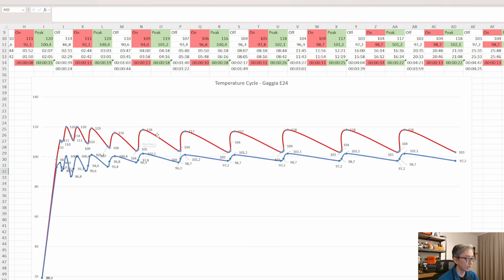In this graph, we have in red the temperature in the boiler, and in blue the temperature in the puck. The temperature in the puck was adjusted, okay? When you see 97.2 is the starting point when the light goes off, 98.7 when the light goes on, 102.1 when the temperature is at the peak, which is 118 degrees in the boiler. So those are the measurements that I made with the thermocouple in the portafilter.